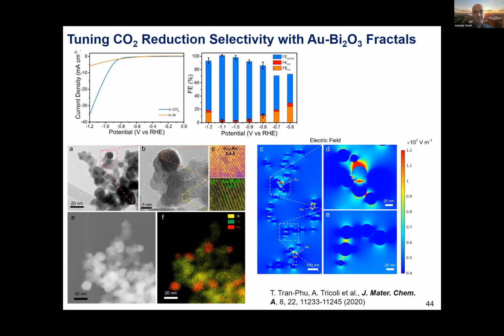So here you see basically a nanoparticle distributed with a fractal structure simulated by particle dynamics. And here you see the electric field forming once exposed to a similar condition as in the electrode.